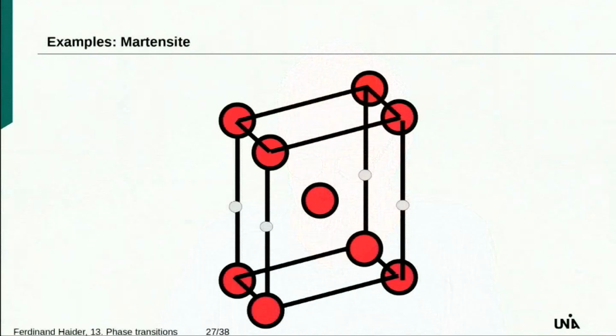Now, just to complete this, what happens in martensite? You know that martensite is a very hard and brittle phase. In principle, the same happens. Where are the carbon atoms located here? They sit on certain interstitial sites, the octahedral sites, and these octahedral sites, they can be put here on the axis, on the side axis of this tetragon.